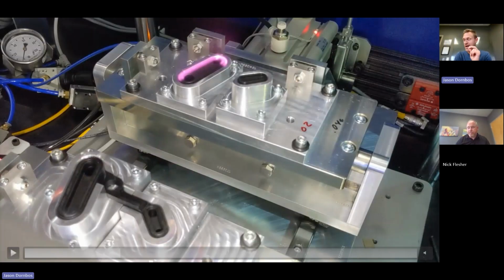Not necessarily peak, but hygroscopic, and how moisture in plastic parts affects IR welding. So, regardless of the energy method that we're using, if there's moisture in the part, as you come up to melt temperature, that is, what you need for welding, the water will boil, and so you can create voids, which then lower weld strength. The water kind of acts as a contaminant. So typically, we see that it's not too much of a challenge if it's run right off the mold.